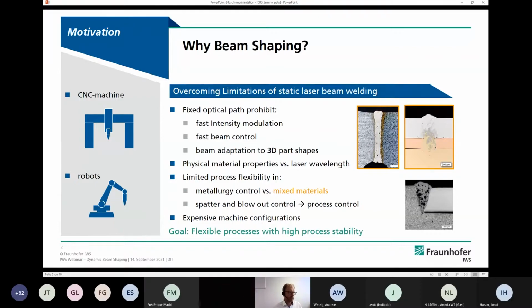If you use only a fixed optical path, you are really demanding on the machine to move the laser beam around the part, and you have no opportunity for fast intensity modulation or even fast beam control. That makes processes slow and doesn't let us work with mixed materials, as you can see here for copper and aluminum, or for other cast steel components. The only opportunity right now to address different intensities or a different wavelength according to the material surface, for example for copper welding, is to use other laser sources, like green, blue or near infrared light, or to use specific optics and optic setups to change intensities.